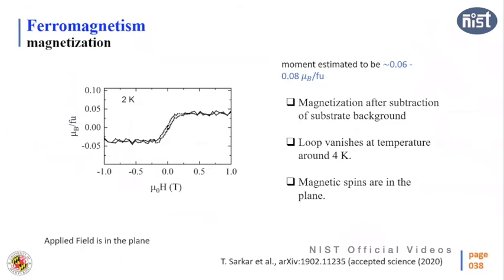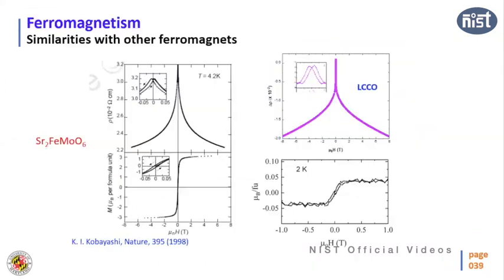Doing a magnetization measurement on a thin film is quite challenging, but we did it. After subtraction of the background, we found that there is a loop. This also suggests that there is a magnetization. So these films are magnetic. Now, from all this data, if we compare with a classic, well-known ferromagnet, we found these loops are quite similar to this. So this could be a ferromagnet.